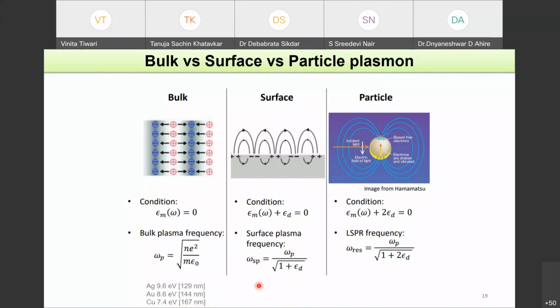But for surface plasmons, the frequency is tunable. You can change epsilon d and shift it towards red. And you can see here, based on the Froelich condition we have seen before, the localized surface plasmon frequency can be further brought down. The frequency is getting down, the wavelength is getting redshifted. So you can slowly push them towards visible and near infrared wavelengths.